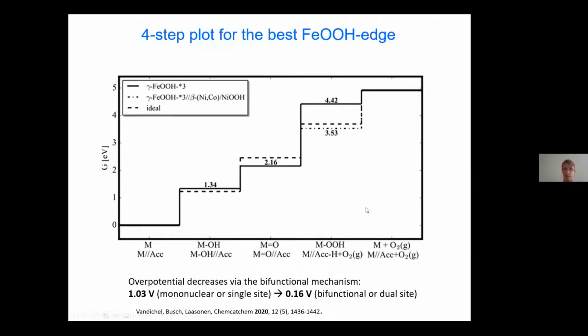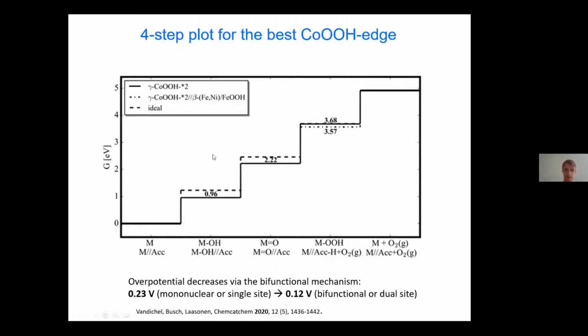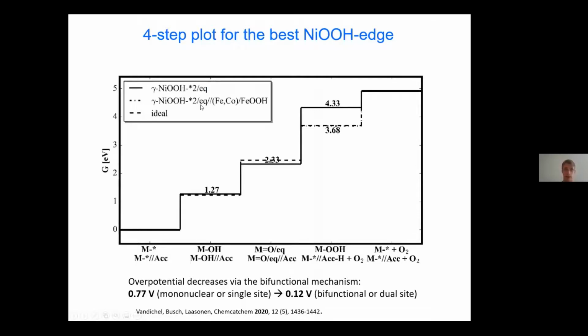And that is what is important. So if we have three metallic systems, now we can know why they lower the overpotential. The same for cobalt. Here we can also lower the overpotential from 0.23 volts to 0.12 volts if we combine it with an iron nickel oxyhydroxide acceptor site. For the nickel, the same. If we combine that with an iron cobalt acceptor site, we can lower the overpotential from 0.8 to 0.1 volts.